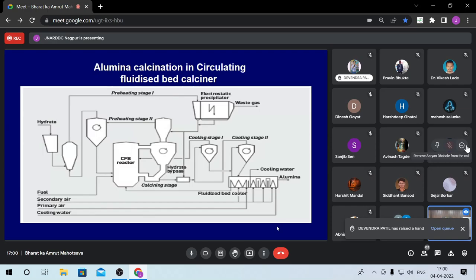fluidized bed calciner. So this is the fluidized bed calciner in which the secondary air passes through it and gets heated, the primary air also passes through this one, and after that the hot air basically comes into this one. The hydrate is passed from the top, and the flue gases which were leaving the system at a temperature of 1000 degrees were wasted in the rotary kiln. But here the flue gases leaving the system are used for heating the hydrate which is entering the system, and this hot hydrate basically comes into the main fluidizing bed reactor.